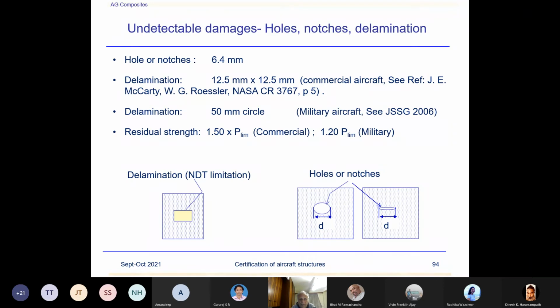Delaminations, half inch by half inch, that's the usual consideration, even though when you are doing the NDT analysis using some probes, you might be able to detect around 6 millimeter, 7 millimeter. However, to be conservative, usually the industry practice is to consider half inch by half inch delamination for civilian aircraft. You see the next line, delamination for military aircraft, 2 inches, which is a fairly severe requirement.